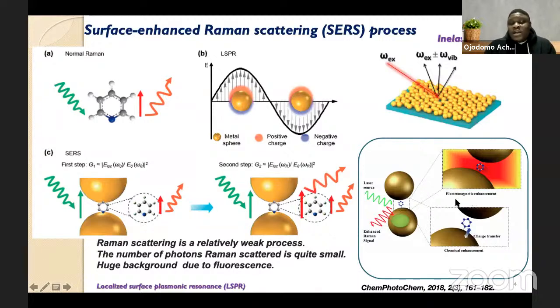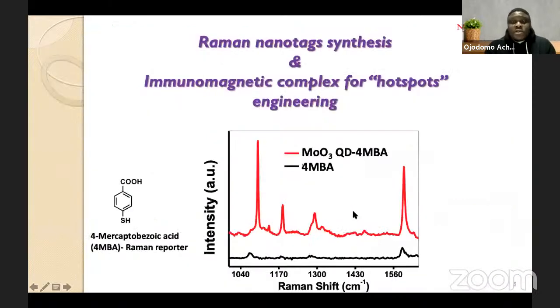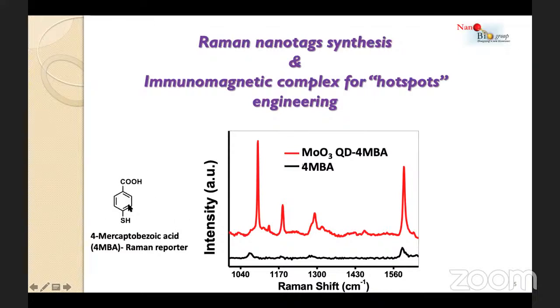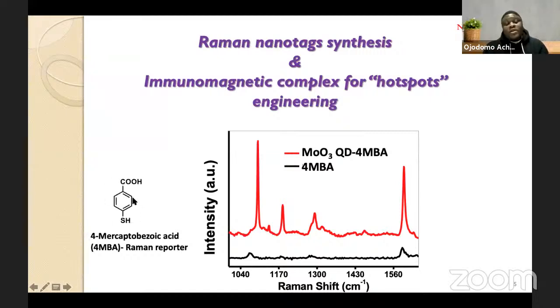What is involved here is the electromagnetic enhancement phenomenon, or the charge transfer, which could result in direct electron transfer from the surface of the plasmonic material to the molecule in question. Or we can see the electromagnetic field effect, which is due to the surface plasmon, that can result in electronic coupling and also enhance the signal of the molecule. Using this very principle, SERS materials, what we refer to as Raman nanotags, have been designed. This slide shows what you can expect by the conjugation of 4-mercaptobenzoic acid, which is known as a Raman reporter because it has a distinct Raman signal that originates from the aromatic ring and from the carboxyl bonds, and the different bonds on top of it.